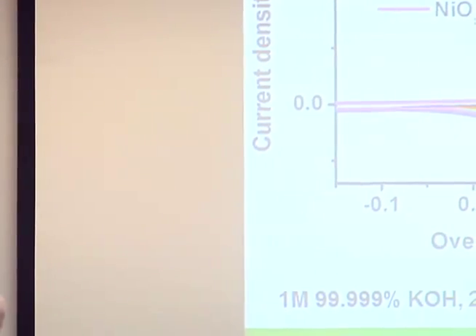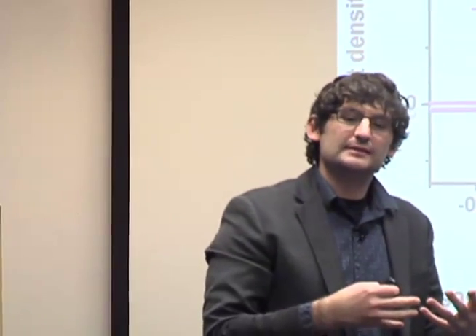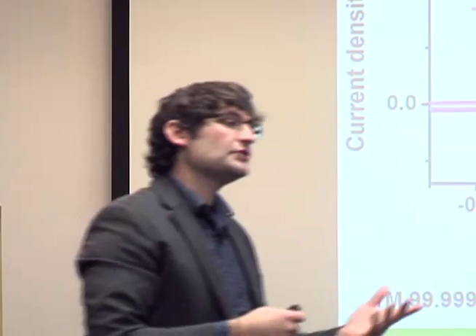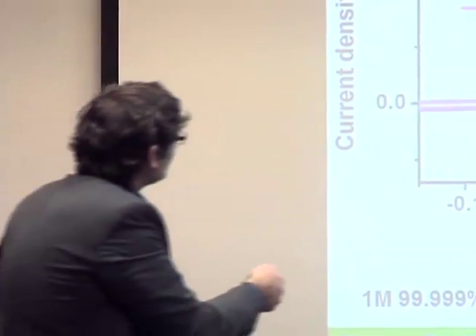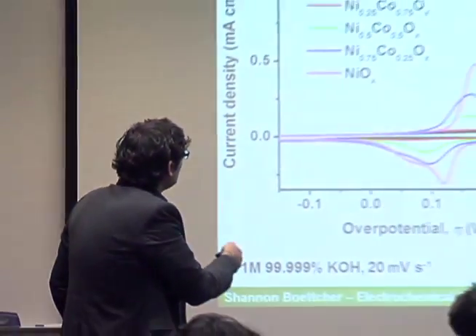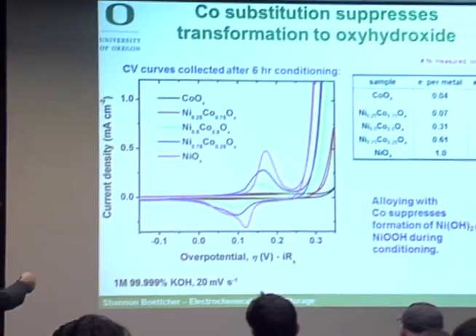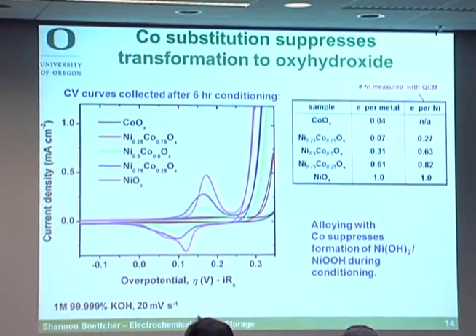If you do the experiment where you look at the voltammetry after conditioning for some time, after allowing the sample to convert to the extent it does to the oxyhydroxide phases, you find that as you add cobalt, for the pure cobalt sample, for example, the film does not show any of this prefeature because there's no nickel.